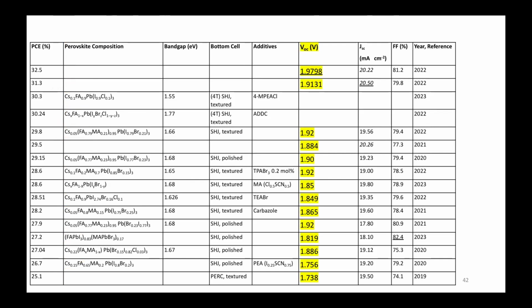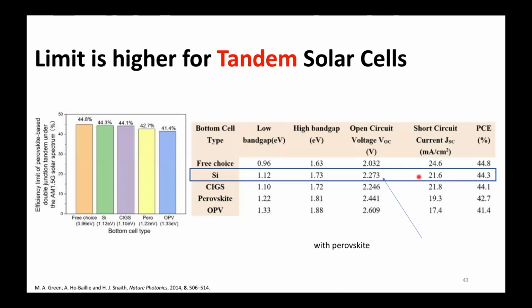You also see that the main gain is the voltage. So as you go from the lower to the top, you're getting to almost 2 volts, starting from 1.7. So the development in the field is leading to better voltages. The currents, they are not changing a lot. They're already like 20.5. So that means for the current, we're pretty close to the theoretical maximum. But for the voltage, there's still a lot to gain, like 200 millivolts. And that's huge.